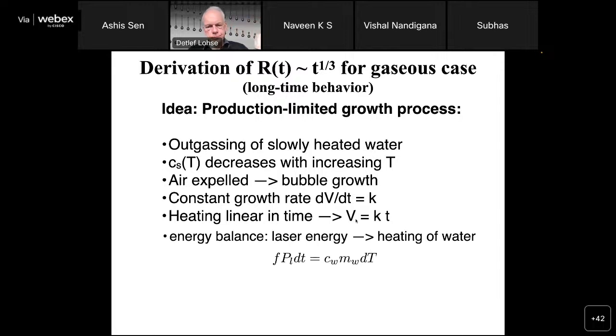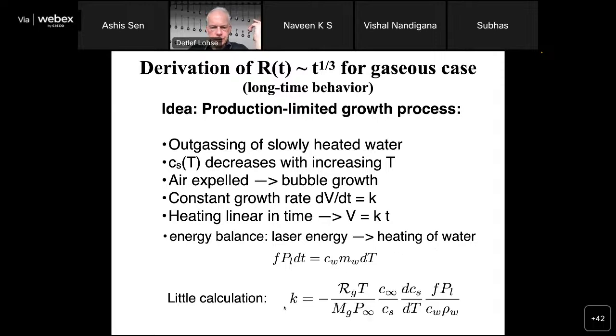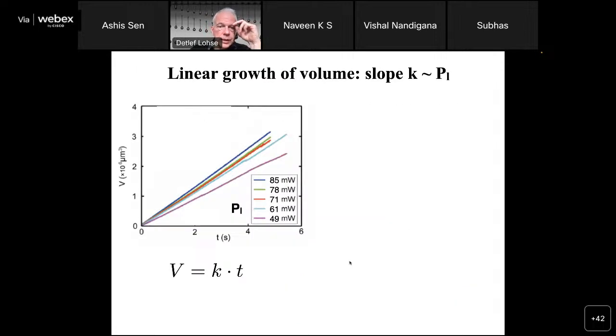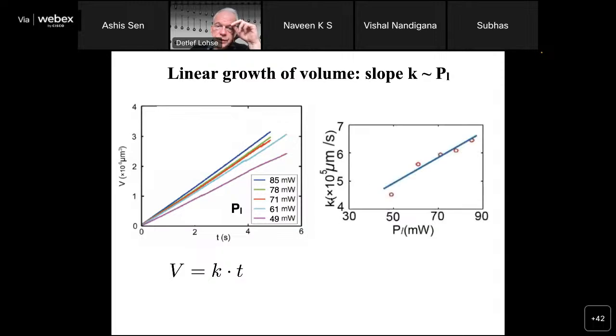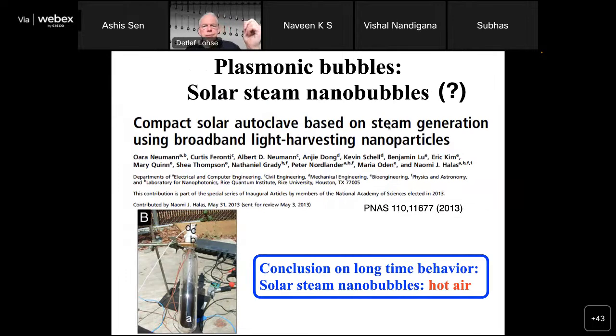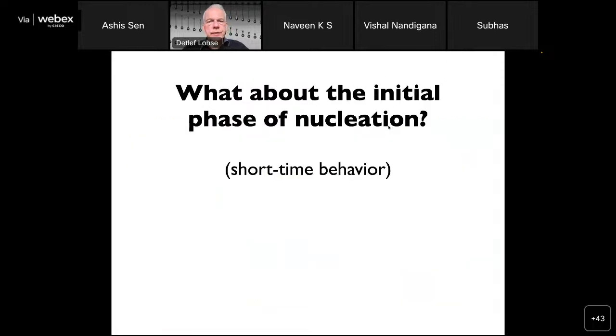So the radius goes like t to the 1/3, and you put up the energy balance, laser energy being put in, and the heating of the water, and out of this you can even calculate the prefactor of this growth process. And this is directly related to this power. When we now look into this prefactor, it is also pretty consistent with what we would expect, that this prefactor is linearly connected with the power which we put in. The conclusion on the long time scale is that the solar steam nanobubble is nothing else than hot air, literally speaking. But what about the short time scale and the very short time scale?